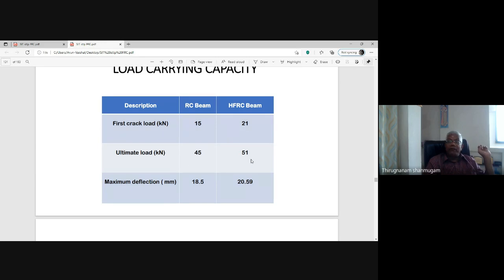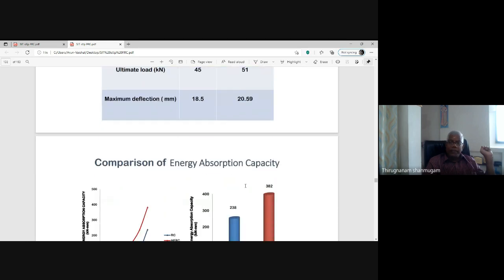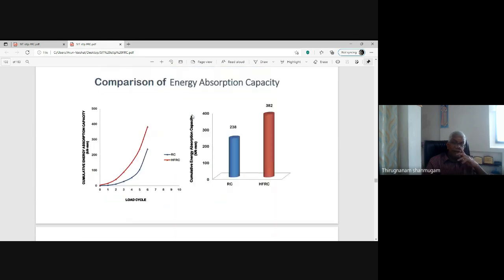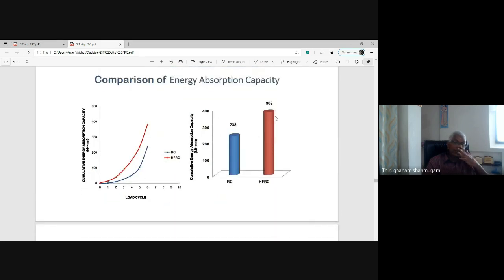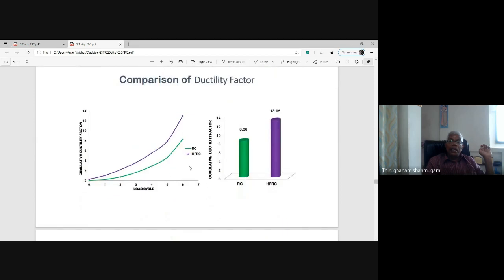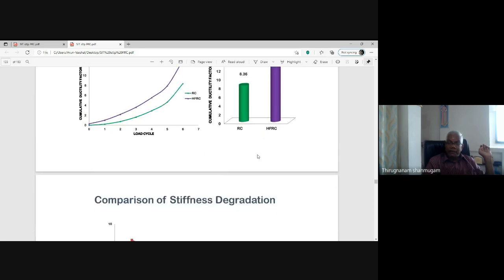Ultimate load 45 and 51, a marginal increase, about 10%. Whereas the deflection is also increased very much, 18.5 mm, 20.6 mm, because at the inelastic stage the deflection is very high. Comparison of energy absorption capacity, 238 and 382. Considerable energy absorption capacity is available in HFRCB. Similarly, ductility factor 8 and 13, a 50% increase in ductility factor.